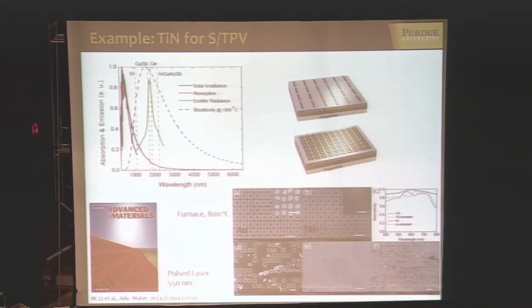You could also make a very selective emitter—that's really important—by using this rod-type structure. It basically acts like a nano-antenna, and in this particular case it's designed so it emits exactly the wavelengths close to the gap of the gallium antimonide photovoltaic cell. You could see it's really close to the peak, and it should show very good performance.